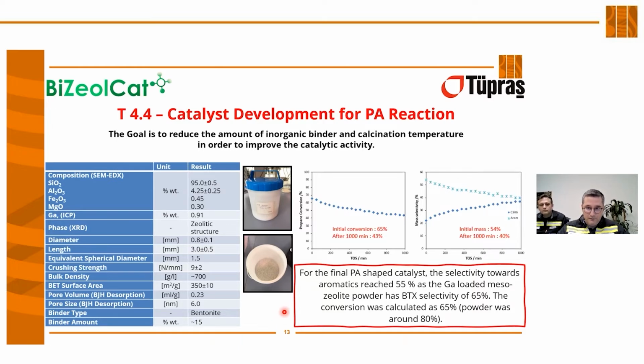For the final shaped catalyst, the selectivity towards aromatics reached 55%, while the gallium-loaded mesozeolite powder has a BTX selectivity of 65%. The conversion was calculated as 65% for the shaped catalyst, and the powder was around 80%. So we reached similar, promising results, but we achieved even higher results after modifying our